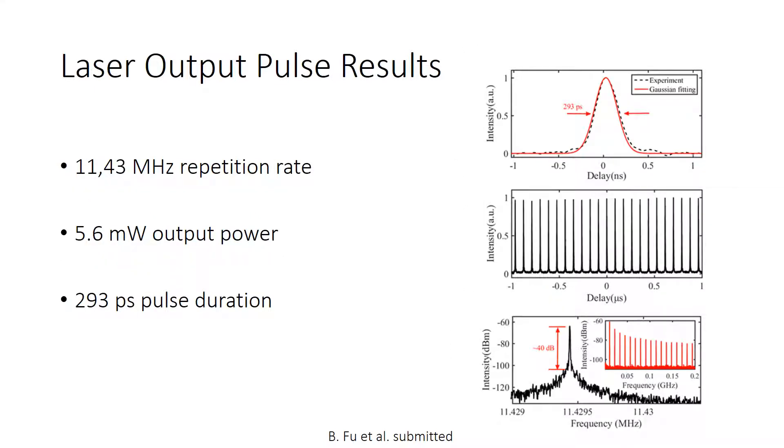Here we can see the laser pulse characterization. We have an 11 megahertz repetition rate, an output power greater than 5 milliwatts and a pulse duration of 293 picoseconds.